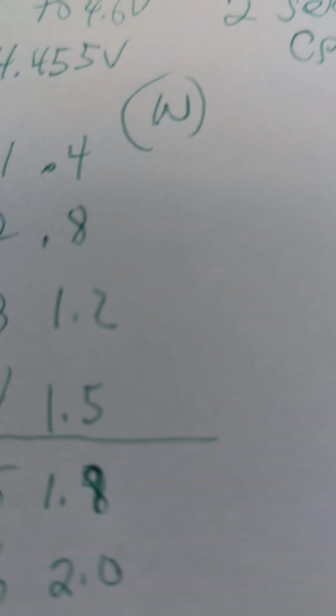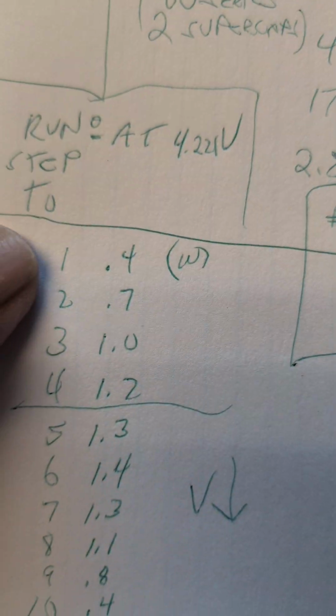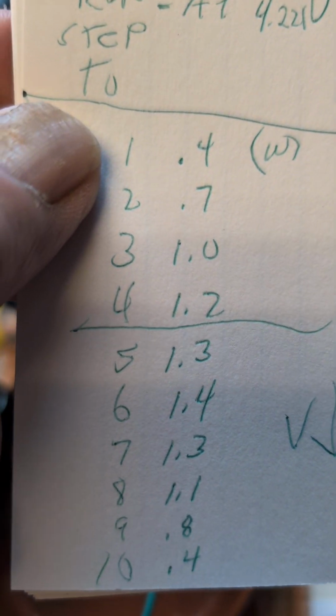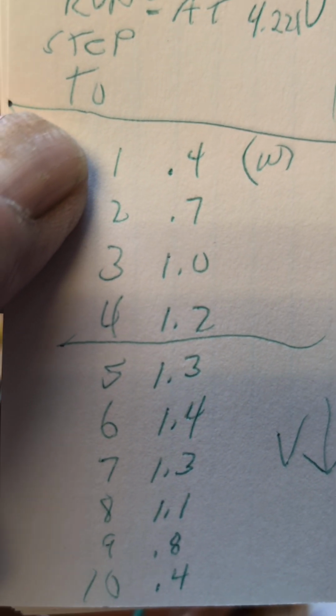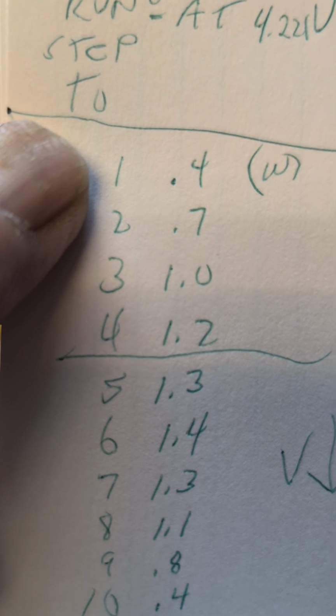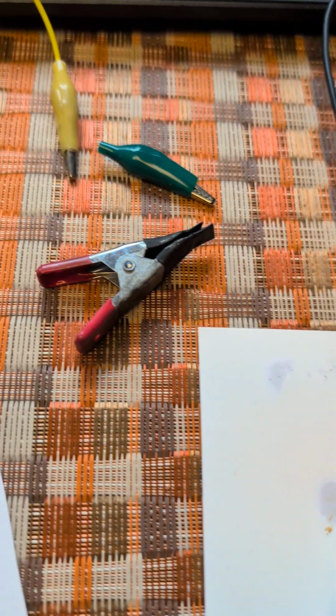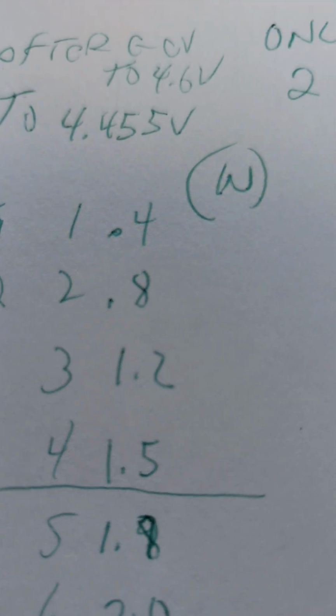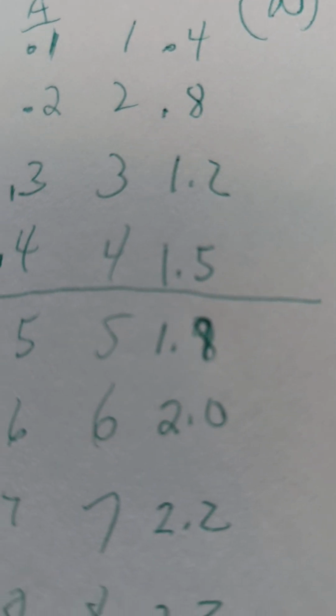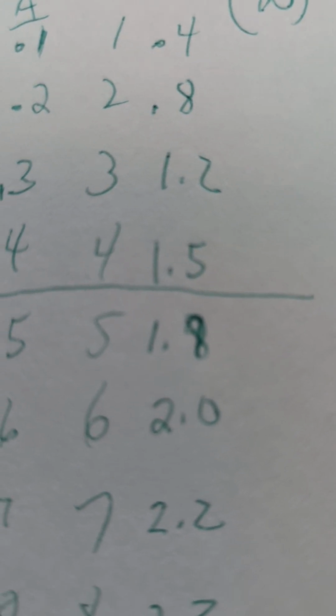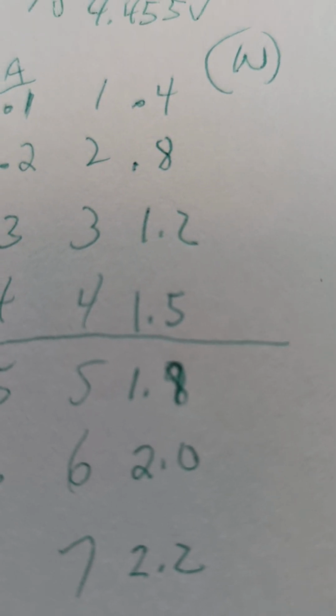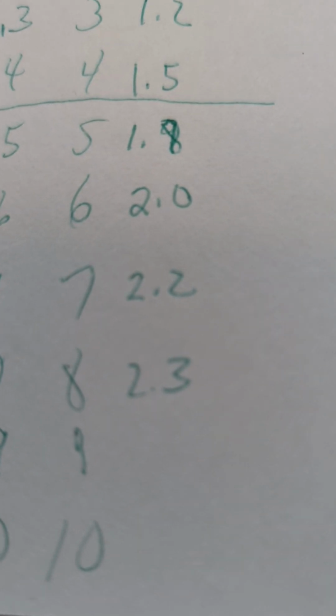That's only the 2 supercaps. Now, once again, with the graphite felt, if you look at these numbers, after step 4 and step 5, you can see 1.2 watts and 5 is 1.3 watts. But if you don't have the graphite component, 4, 1.5 watts, 5, 1.8 watts. And then it's going up to 2.0, 2.2, 2.3. Now that's with only the 2 supercaps.